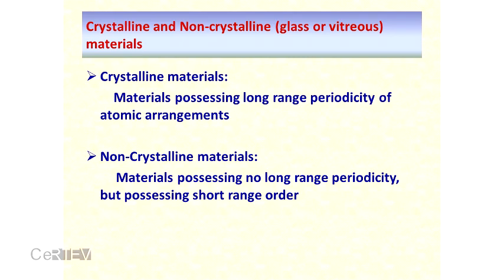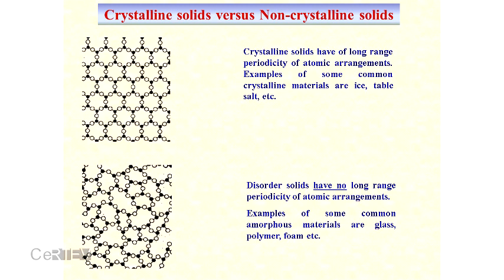It has already been shown that glass has no long-range structure, as the crystal has. I have shown it here because you can see the difference between the structure of crystal and glass. One thing, there is no drastic change. If you pick up, this is practically the silica, two-dimensional picture. The silicon is surrounded by 3 oxygen here. When it is in the glassy state, you can see the same thing is happening. So there is no change in at least the first coordination number. And this is the point I want to mention.